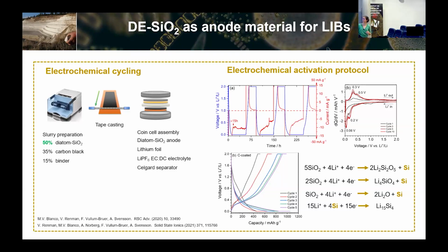And what you see here are these potentiostatic holding steps. And you see the increasing capacity we got over 5 cycles. After 5 cycles, the capacity was stable. This is not great. It might be that this material, the silica, cannot be used as such as an anode, but this is part of the learning curve that we went through.